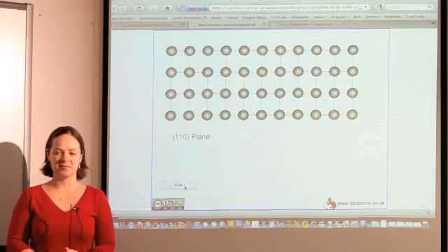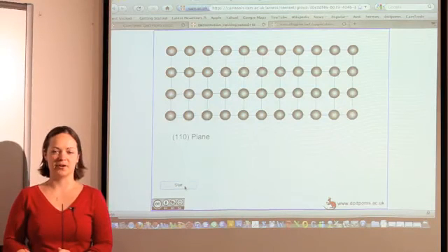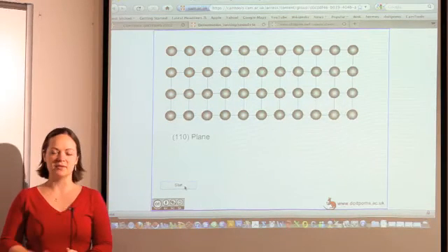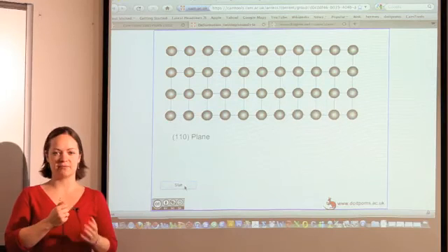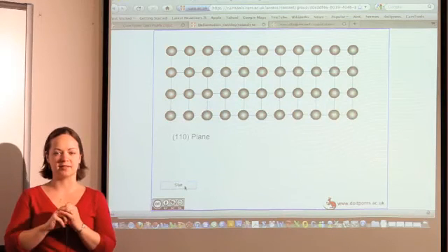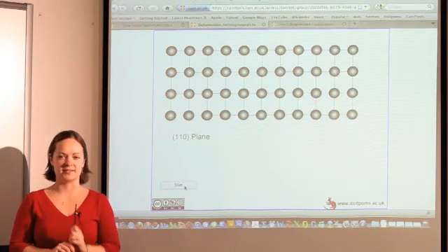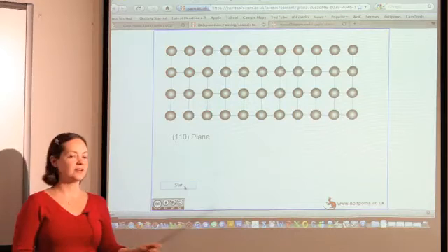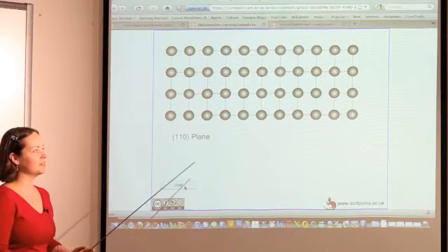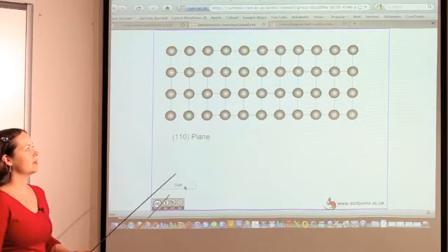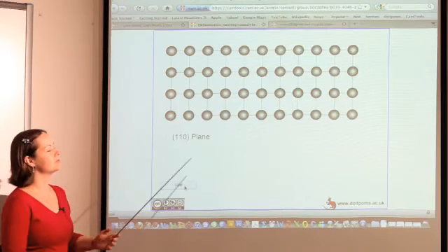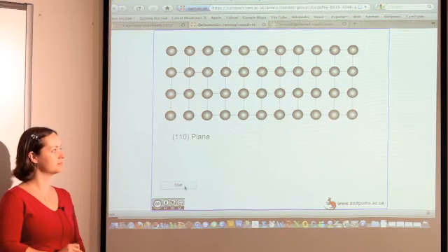We'll consider the room temperature case first. When I bent the bar, deformation twinning took place, and we heard a characteristic crackling noise known as tin cry. The reason we heard this noise is because during deformation twinning, the atoms move very rapidly, all at the same time, which generates a sound wave. So this is illustrated schematically in this very simple animation. When we press start, a twin will be formed, the atoms will move, and a sound wave will be generated.